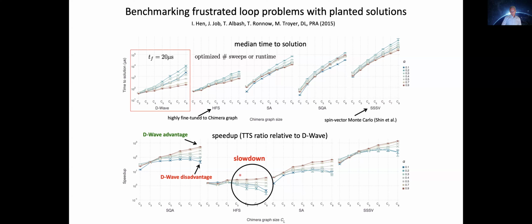But unfortunately, relative to HFS, this highly optimized algorithm, there was no evidence of a speedup. One might claim, if you set aside concerns about optimal anneal time, an advantage over SQA, let's say here for the high clause densities, the color scale is the clause density. But for D-Wave versus HFS, again, there was no evidence of a speedup, basically just slow down. Okay, so this didn't work either.